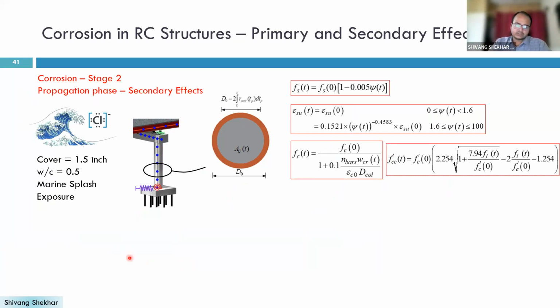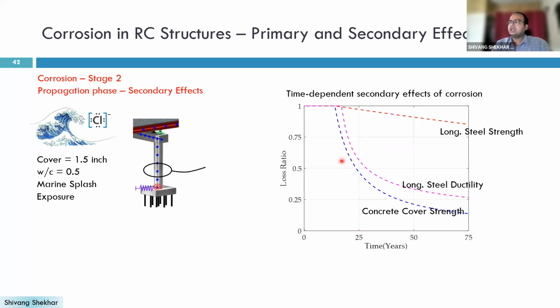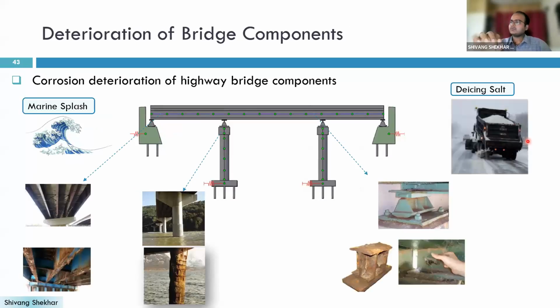So we have also tried to look into the literature and see how people have tried to model this based on the percentage mass loss of steel. So these are some of the equations that can be used to see the secondary effects of the corrosion. And then we try to plot how, across the service life of the bridge, how much will be the degradation or the loss in the concrete cover strength, loss in the steel ductility, loss in the longitudinal steel strength and all. Now we have seen the corrosion of bridge piers.